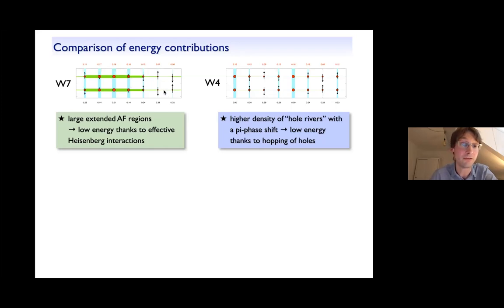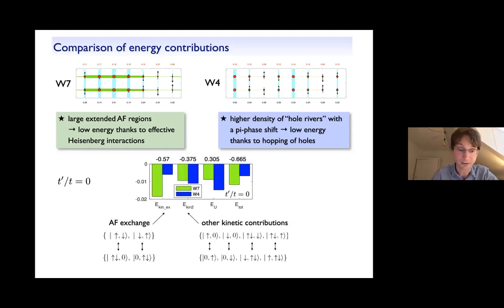So if you think in terms of an effective t-J model, the J term will give a low energy in this region. The period 4 stripe is worse in this respect because it does not have these large extended antiferromagnetic regions, so the doping here is also higher. But what is better for the period 4 stripe is that it has a higher density of these domain walls of the holes, which is good to minimize the kinetic energy of the holes, which can nicely fluctuate on the boundary, right? So each stripe has its own advantages and disadvantages from an energy point of view. A priori, it's not clear which of the two is going to win. So let's have a look at the actual numbers.